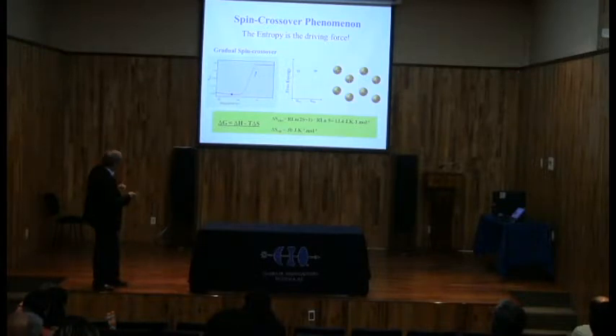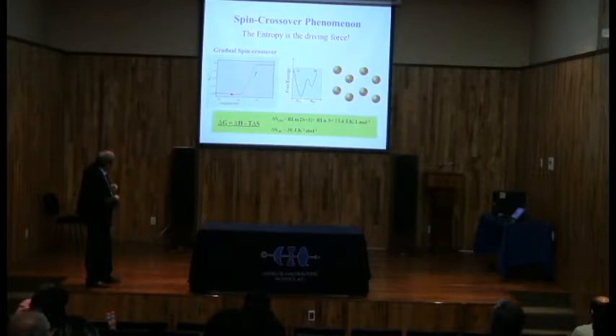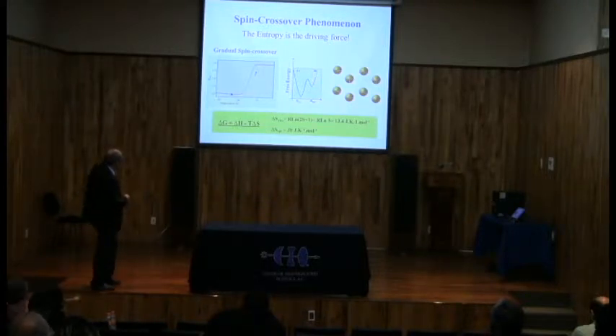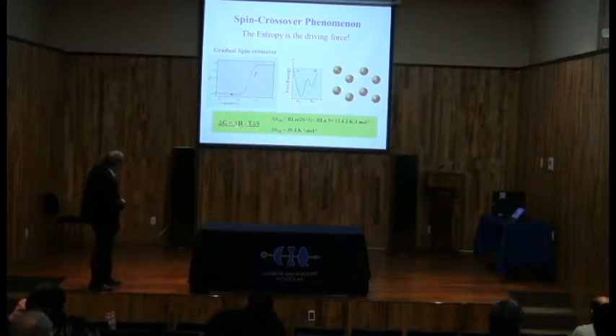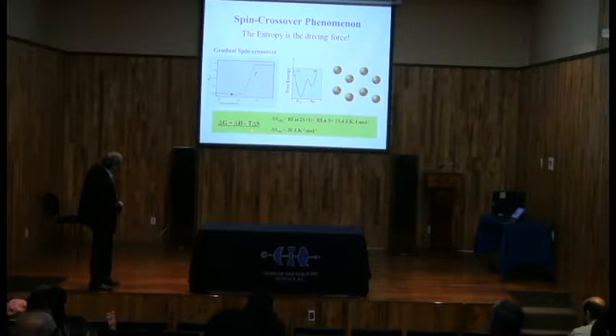If you look at the free energy of this system, at this temperature the low spin state is more stable, and then you have a double potential. The free energy of the system is delta G equals delta H minus T delta S. Here the enthalpy of the system is constant, and the entropy change, electronic or vibrational, is also constant. The only parameter here is the temperature.